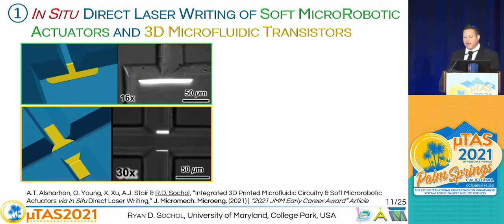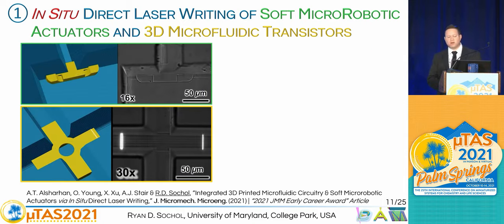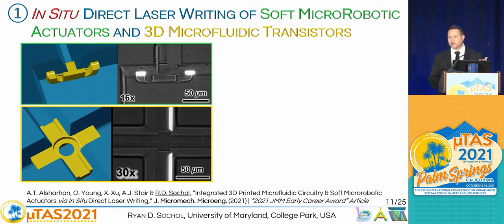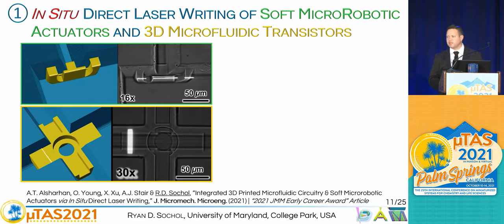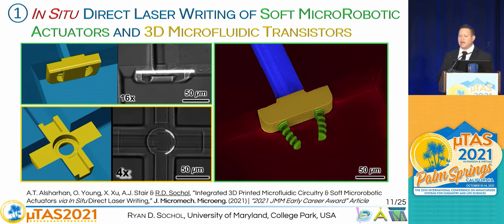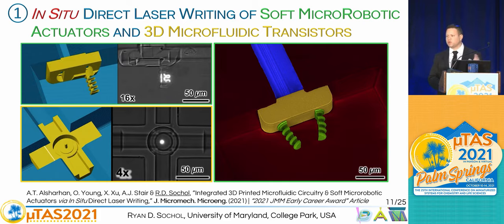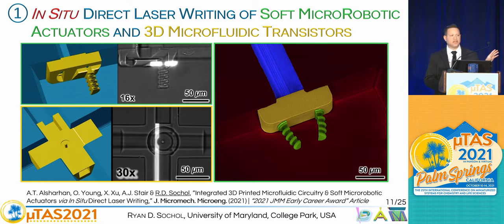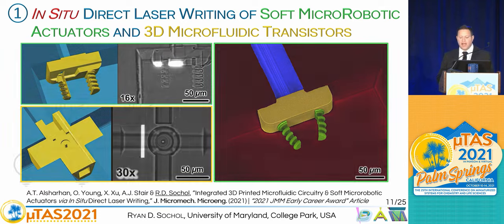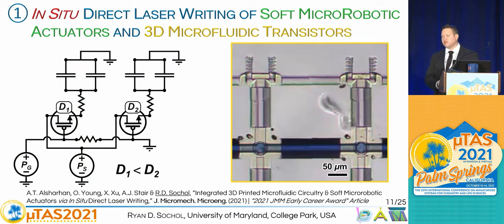So this is the manufacturing process for these particular components. At the top, you can see the soft microgrippers. At the bottom, you can see the microfluidic transistor. And then this is a false-colored SEM, just again to highlight the scale at which we're printing these, right? So these actuators here are on the order of about 10 microns. And so here you can see an analogous circuit diagram next to the actual manufactured component.